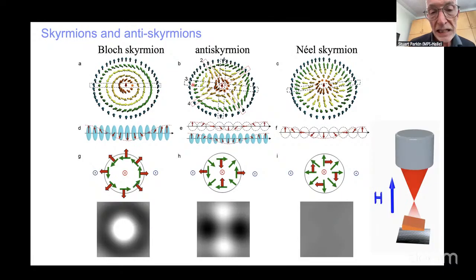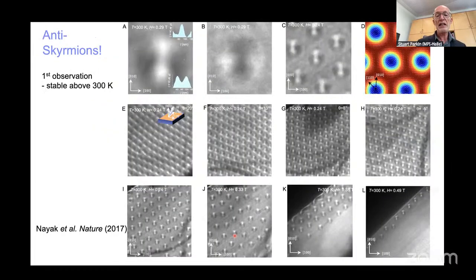On the other hand, in an antiskyrmion, we calculated that we would see this very interesting clover leaf shape-like object with two white regions of increased electron intensity and two black regions of decreased intensity. And actually, that's what we observe. If you look on the top left in A, you can see the first antiskyrmion that was observed by ourselves at room temperature in a Heusler compound, manganese 1.4 platinum tin.